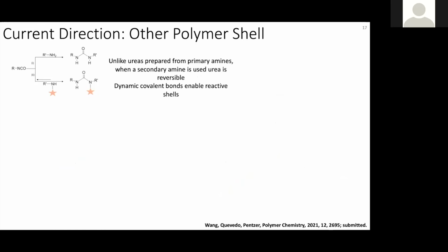And so Yifei actually, I said, well, what if you make these capsules, you treat them individually, and then can we destroy the polymer shell, or can we fuse them into a monolithic structure? And so for that, Yifei turned to hindered urea bond chemistry, a type of dynamic covalent bond. So if you have an isocyanate and a primary amine, they react, they form a urea, very stable, and they typically decompose before any reverse reaction is observed.